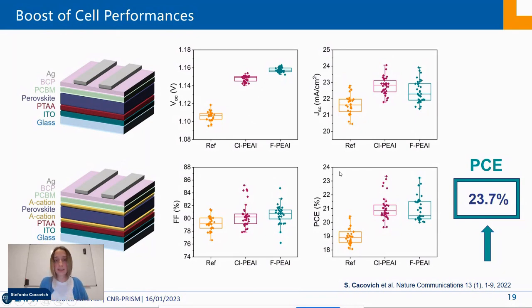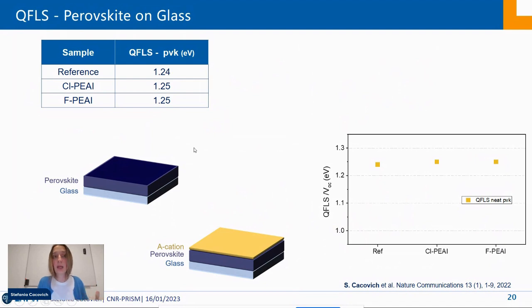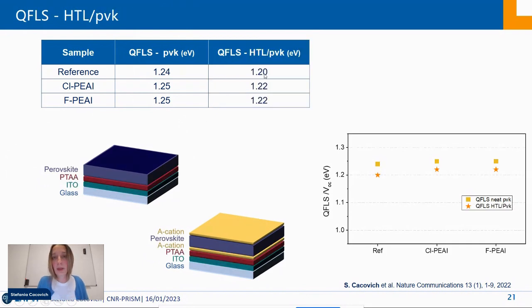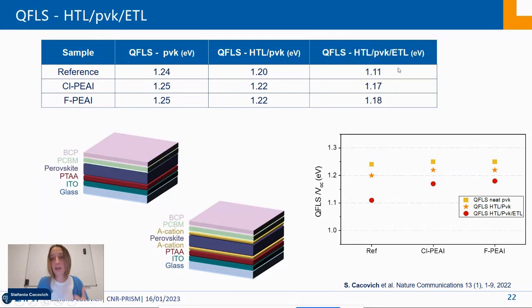So what we try to understand is how the introduction of this cation has modified the physics of the interfaces, and also if the deposition was homogeneous over the surface of the absorber. To do this, we went layer by layer, because this is also one of the advantages of this technique. They are contactless. Therefore, we can use them at any stage of the fabrication of the solar cells. So we can study the bare absorber, but then we can add the different interfaces and quantify the non-radiative losses at each of these interfaces. So we started by calculating the quasi-Fermi level splitting of just the absorber, and then we compared this with the value of the half cell and finally of the full cell.